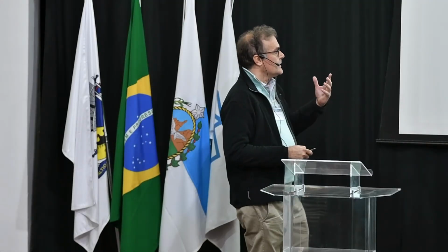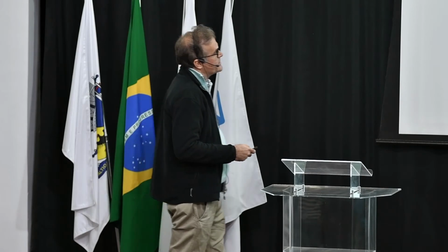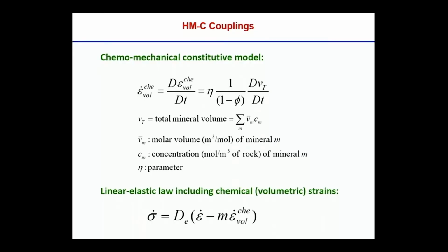Okay, so let's now see what happens with these samples if we apply some stress. To do this, we include in our mechanical model a new deformation that we call chemoelastic deformation, which is proportional to the total mineral volume. This is a parameter that we can obtain experimentally. You can use this law for two situations: crystal growth or chemical compaction, if you have precipitation or dissolution.